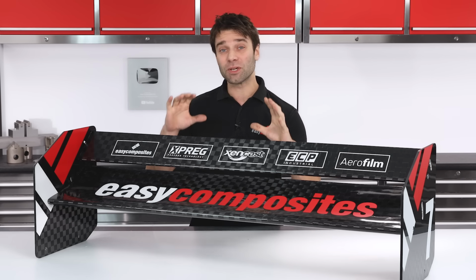Simple spars can be made by slicing the core vertically and bonding in some pre-made carbon sheet. Of course, you could add further complexity by including spar caps and even ribs. The fibre type and orientation in this wing could also be improved. A simple 0/90 layup of a woven cloth will not yield the strength and stiffness that could be achieved with more careful placement. While experimenting with these more optimised constructions can be a lot of fun, they will add to the project's complexity and completion time, and it's really up to you if you deem them to be worth the effort.